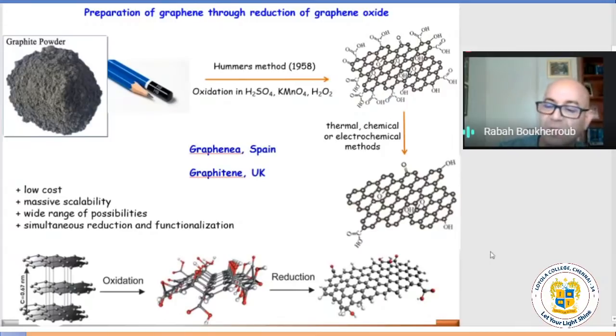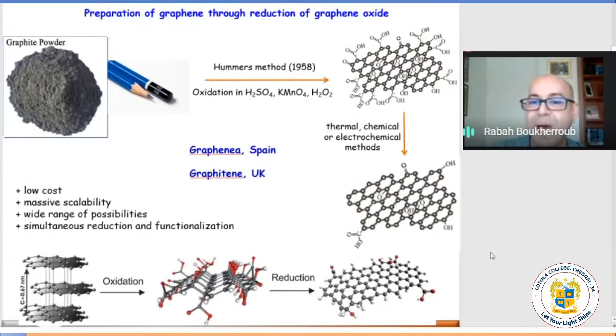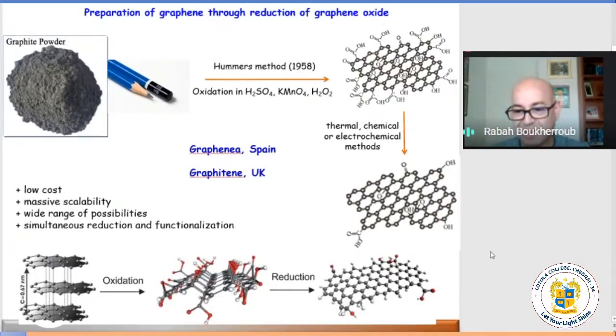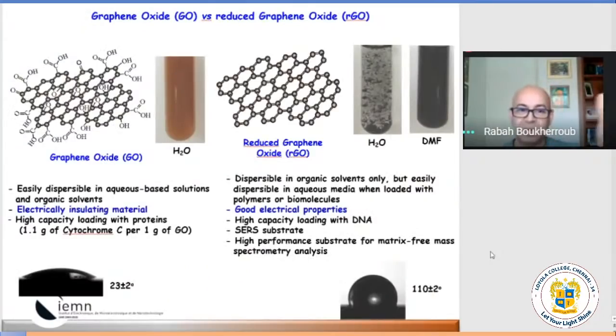Then you have to reduce and remove these carbon oxygen containing groups. The problem is, if you remove all the oxygen containing groups, then you are coming back to the initial material, which is graphite, because you have the stacking. It's exactly what graphite is. So you have to be careful that you don't remove them completely, or you have to stabilize the material so that you don't go back to graphite. Otherwise, you're just going both ways, losing your time and energy and money, of course, without making the real material.